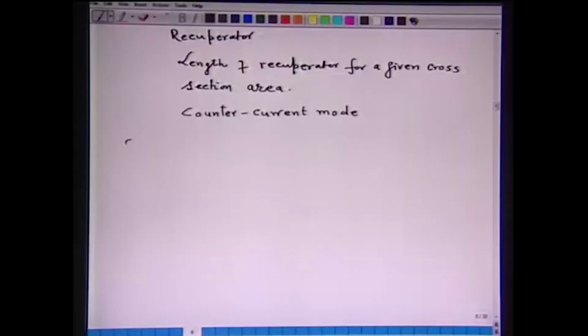Now, as regards the operation, say conventional operation is for 60% hot metal. Carbon is injected to take care of the heat balance, and the waste gases which are produced through the refining of carbon to CO enter into the stack at 1300 degrees Celsius and preheat the scrap. After that, the gases at 800 or 850, whatever the temperature, enter into the recuperator, discharge around 300 degrees Celsius, and then the preheated oxygen enters into the furnace. This is, for example, when you use 60% hot metal and somewhat 40% scrap.